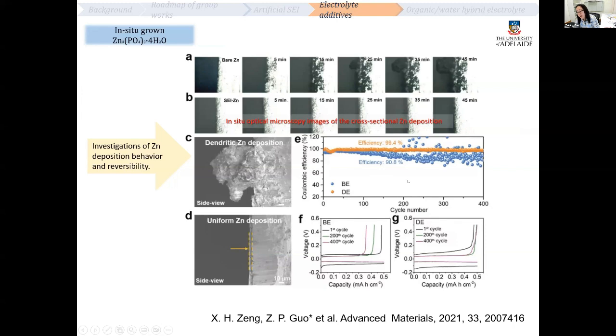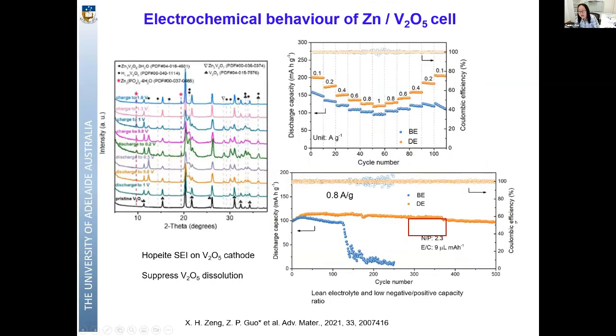For the zinc copper asymmetric cell, it can achieve 99.4%. And the amazing thing is we found that this zinc phosphate not only formed on the surface of the anode, but also on the cathode. In this case, we use vanadium pentoxide as cathode. We can clearly see peaks corresponding to the zinc phosphate. So this layer helped to suppress vanadium pentoxide dissolution. Therefore, it played a positive role on both anode and cathode material.